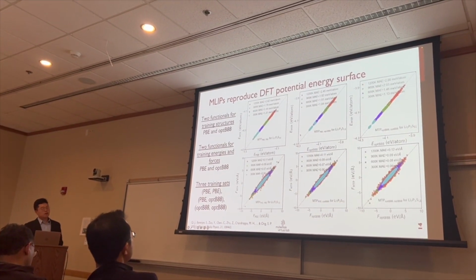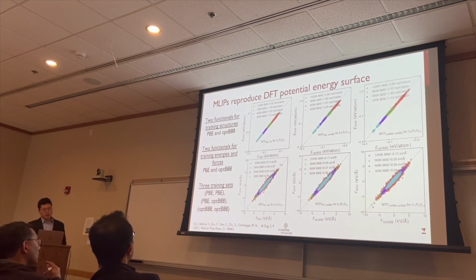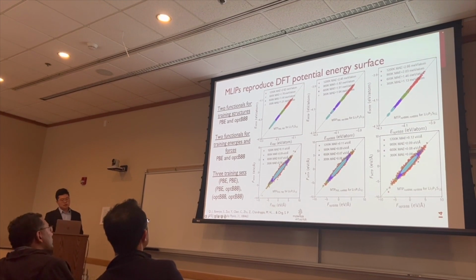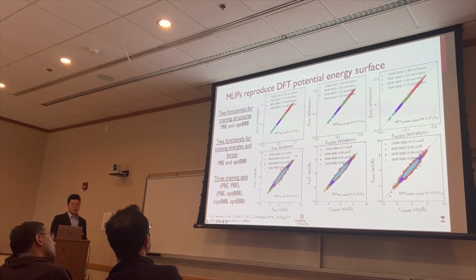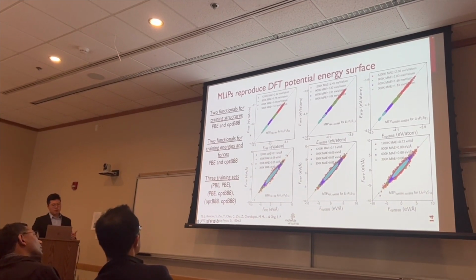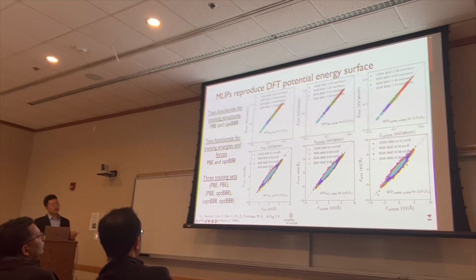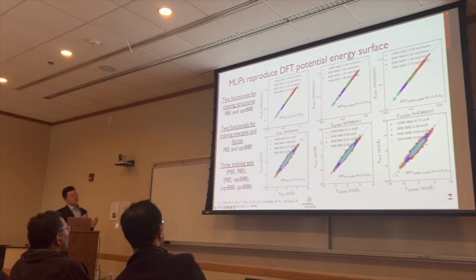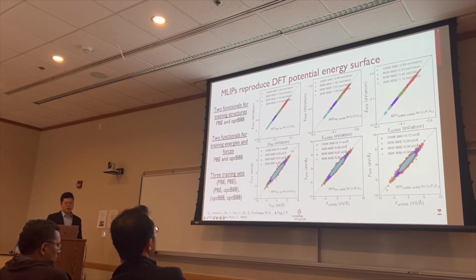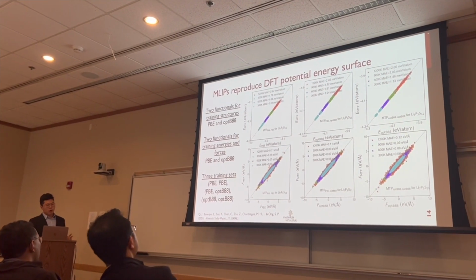So with those training data, we fitted moment tensor potentials for these 3 systems. Here, as an example, we show for the LPS system in the parity plot that for both energy and forces, all those 3 moment tensor potentials reproduce the DFT result with very low error, which is a mean absolute error of below 3 meV per atom for energy, and for force it's around 0.1 eV per angstrom.